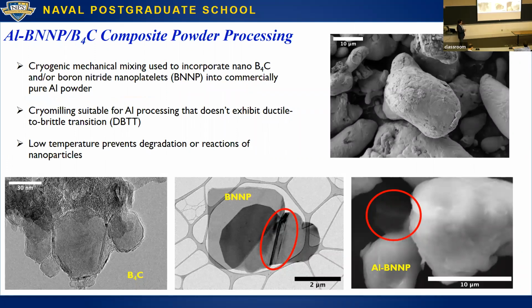So we're trying to make composites that make use of dual nanoparticles so that we can get both strengthening, but also try to get some useful properties. And what I'm going to show briefly here, we used boron nitride nanoplatelets because it's a large surface area, ceramic phase, relative insulator. And so the idea is that we were trying to incorporate this phase to decrease the conductivity of the coating itself, so we could try to decrease the corrosion process, try to short circuit that corrosion process a little bit. And we got some interesting results.